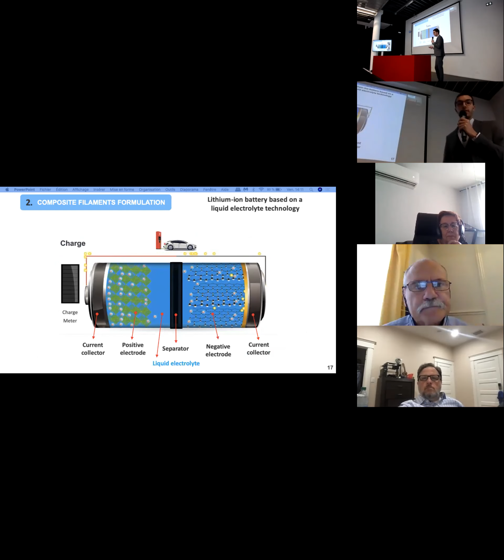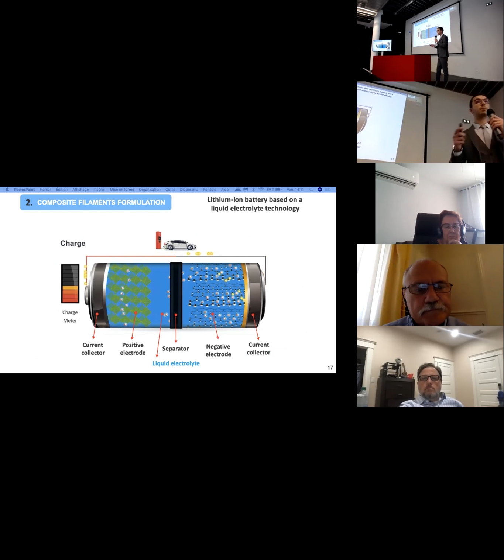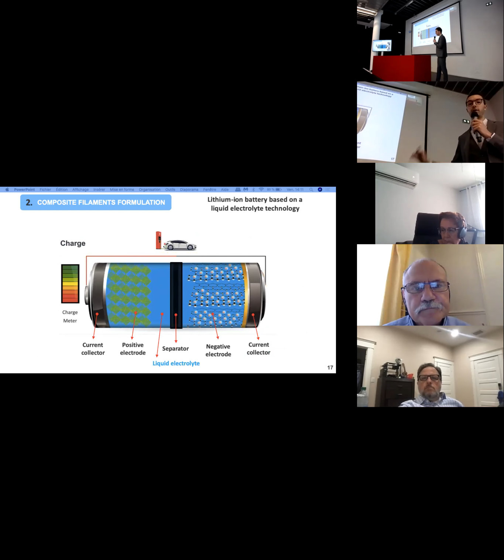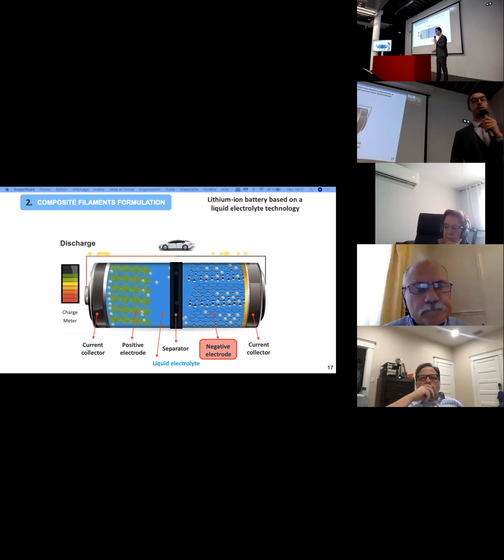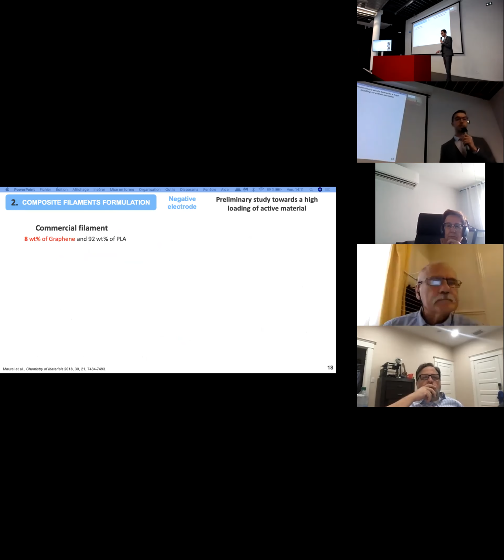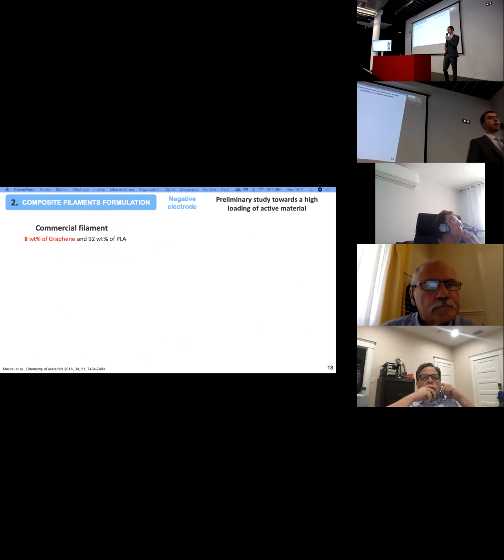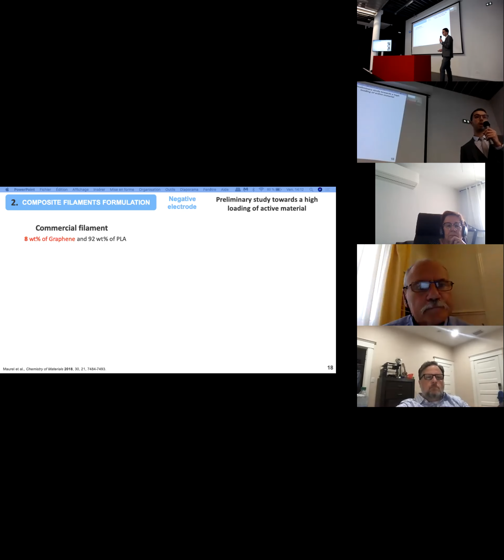So I would like to remind you that at the beginning of this thesis, we just focused on the filament formulation regarding liquid electrolyte technology, okay? And first of all, we started by developing the filament for the negative electrodes. Before starting to develop this filament, we took a look at what was available on the market. And we saw this commercial filament that had 8% of graphene and 92% of PLA. Unfortunately, right from the beginning, we were thinking that 8% of graphene would be maybe a bit too low an amount of active material to confer good electrochemical performance.